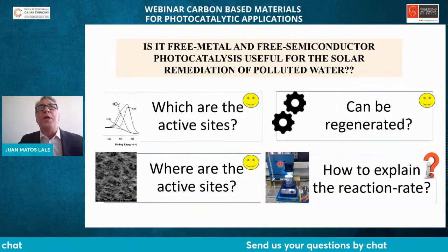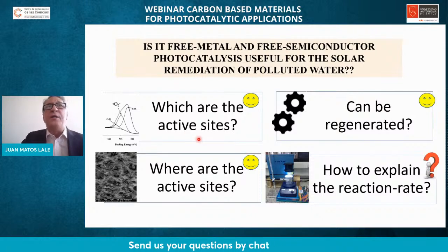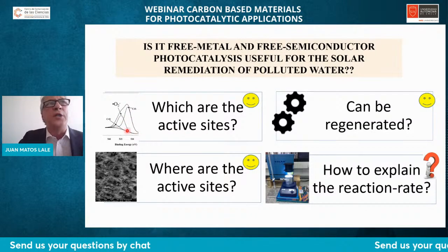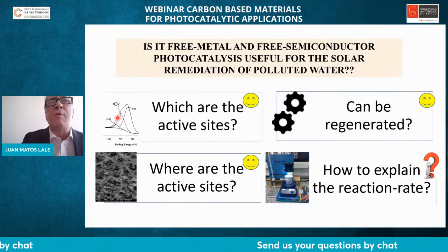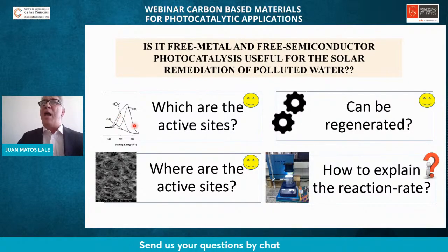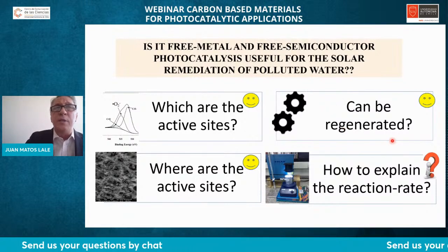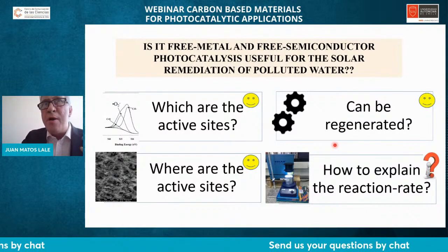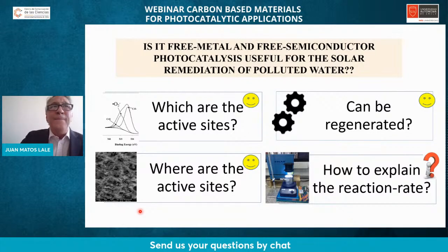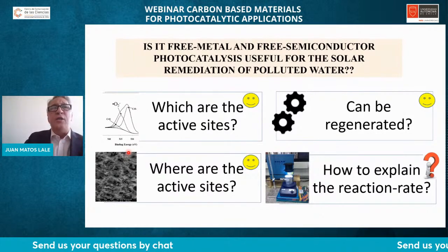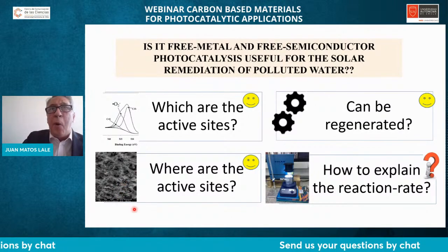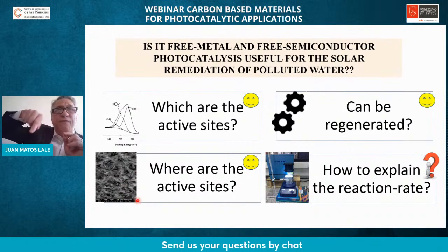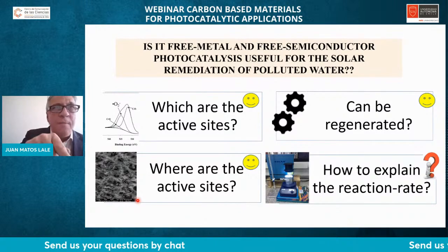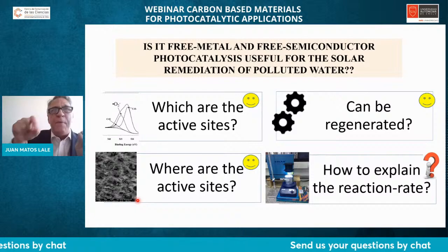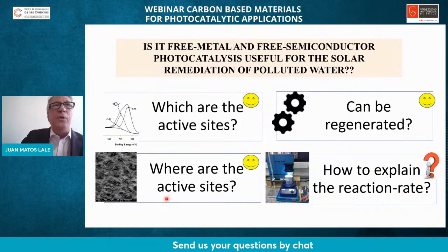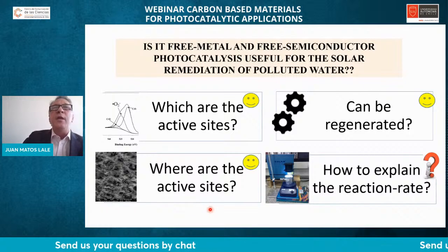We think yes, we are able, because now we know which are the active sites, and most importantly, not only superoxide ion, but also hydroxy radical that are formed in the surface of the carbon. We have already demonstrated that can be regenerated. We demonstrated in a paper 2 years ago. And more importantly, we know now that the active sites are not only in the surface, they are intercalated in the pores. It means that the higher the pore confining effect and the possibility to form oxygen or nitrogen or sulfur basic species within the pores, we are able to induce very high reactivities in carbon materials.